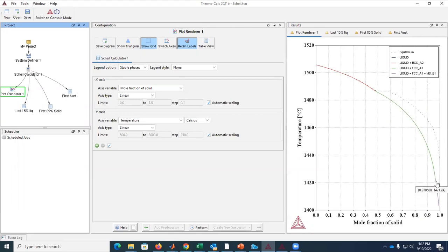And at the end of the solidification process, actually a sulfide precipitates. In this case, it could be manganese sulfide, right? And you can check the composition as well, which you are going to see is rich in sulfur and probably manganese. So this is going to be a manganese sulfide. At the end of the region, you obtain a precipitation of manganese sulfide.